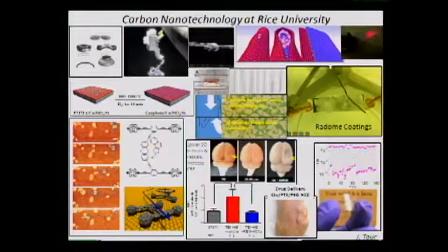And then another thing that we did is we found that we could take carbon nanotubes, multi-walled nanotubes in particular, and we could treat them in two different methods. One is with potassium permanganate and sulfuric acid, a mixture that was developed and used in the 1800s. And also just potassium metal. We could just mix it with the nanotubes and heat it up to 250 degrees, and that would split the carbon nanotubes, and they split longitudinally, just like if you have a pipe in your home and the pipe freezes, the water freezes in the pipe and splits it, never horizontally, but always longitudinally. And that's how these ribbons then form.